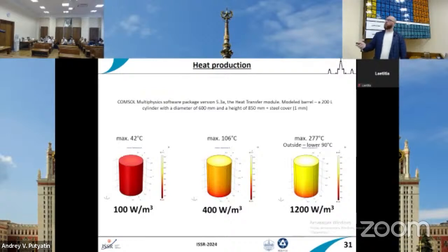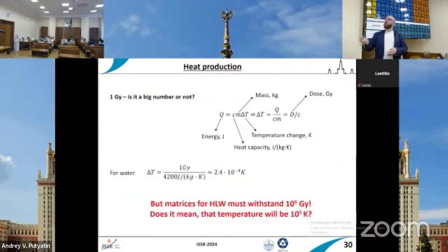Even for these high numbers in cement, which is not really a perfect thermal conductive material, the temperature inside will be not higher than, let's say, 300 degrees Celsius, and outside on the walls it will be only 90 degrees Celsius. So the thermal conductivity results in the transfer of heat from the material, and even for such high doses, of course, the temperature will not be like 100,000 degrees.